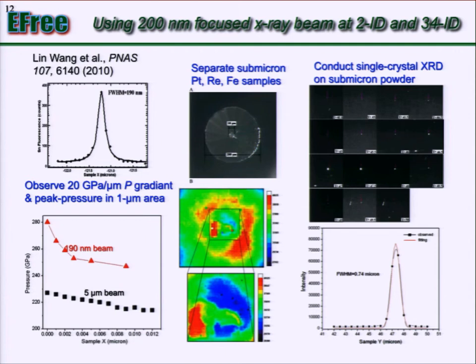Okay, now I'm giving some examples quickly. Here I want to emphasize that for synchrotron X-ray, 200 nanometer became routine. In the past, at most synchrotron beamlines in the world, we used micron size. Why do you need a smaller size? Because if you want to get a higher pressure, one way to do it is to have a much smaller tip. Force per unit area is pressure, so if you have a smaller area, you have more force. Once you get a smaller area, that's a way you can preserve this sample environment at higher pressure. So far, we haven't reached much higher than 300 GPa.